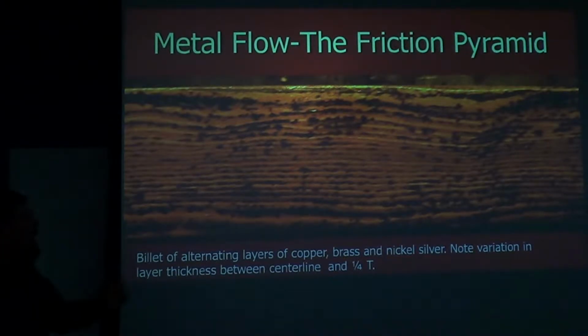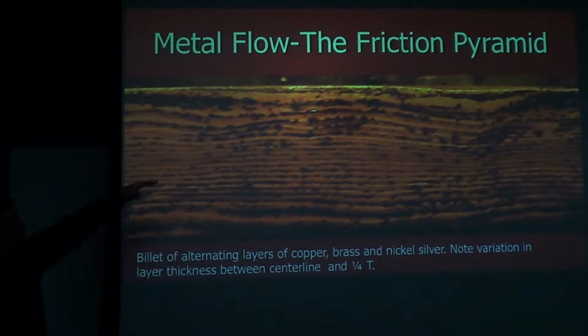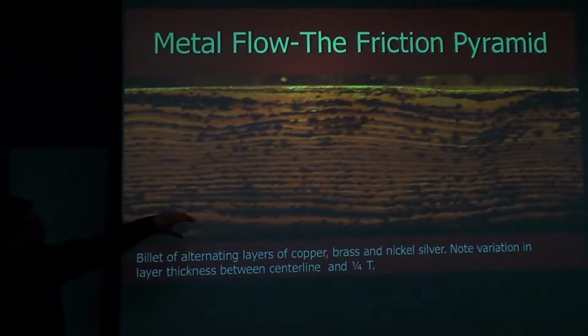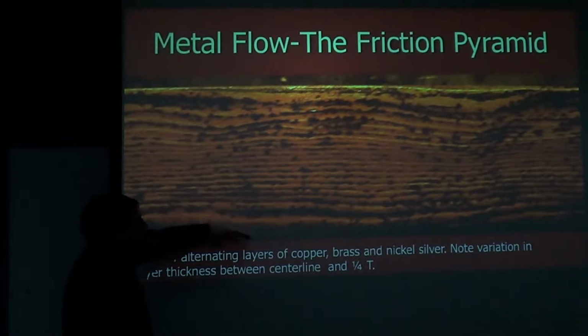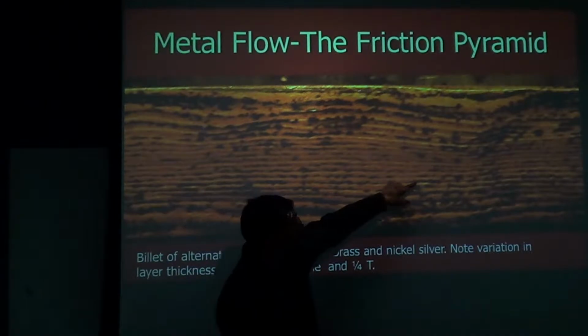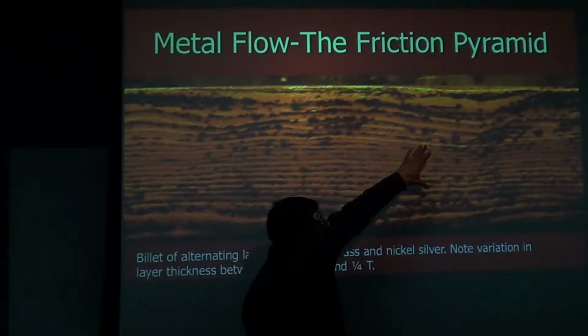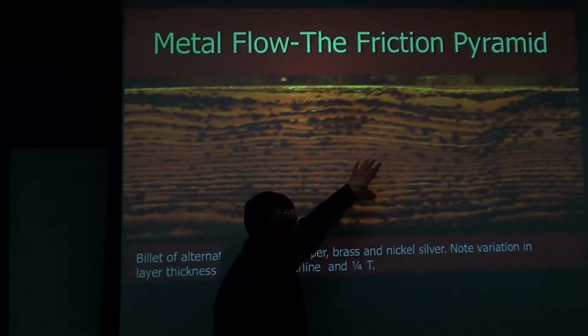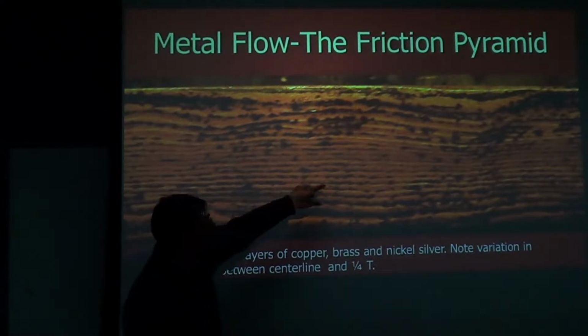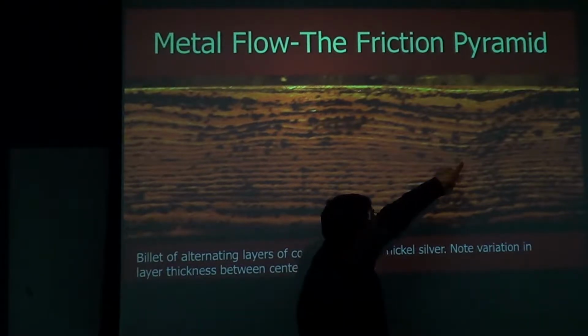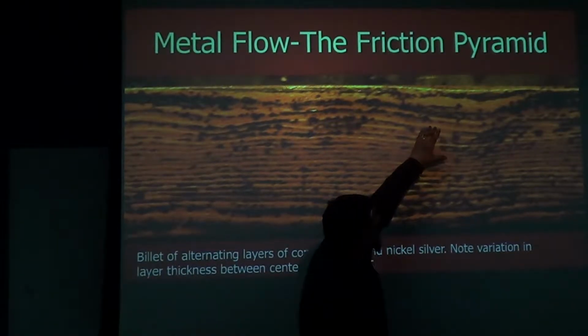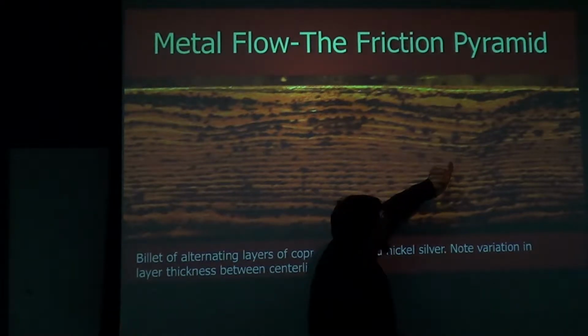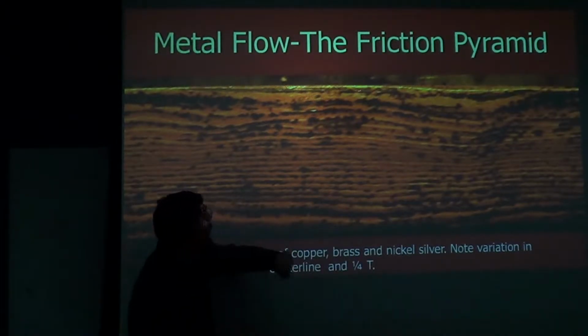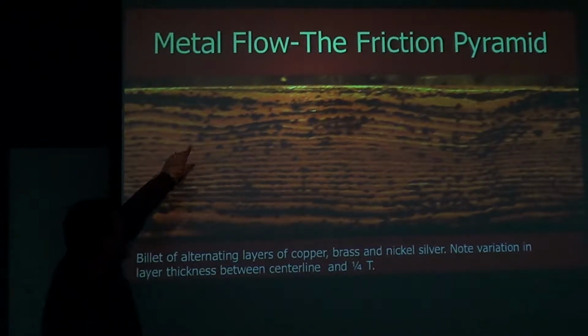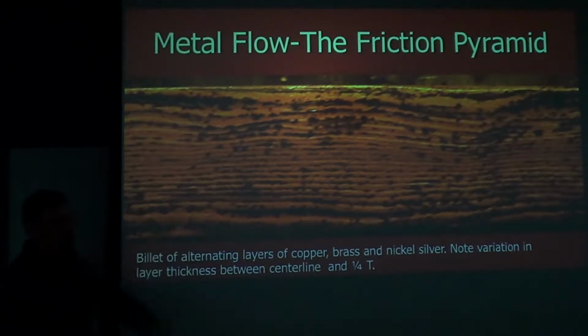Here's some laminated material that I worked with at home. We've got multiple alloys, so they have different colors. And you can see that even though the cross-section is uniform, the individual layer thickness varies depending on where I was forging and how much force was applied as I did that process. So we can see that we have narrow layers here, wide layers up here. This area was trapped by friction. This area was not, and so it was free to be compressed as the hammer came down. You can see there's another less clear section right here where that same thing happened.